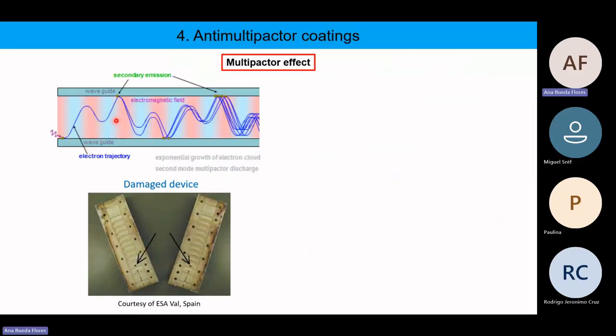So it is accelerated by the radio frequency field, and when it crashes into the walls of the waveguide, it creates secondary electrons. These secondary electrons start with low energy, but then they are accelerated by the field, and when they crash, they create new secondary electrons. So at the end, you can have a cascade of secondary electrons. The least dangerous scenario is just an electromagnetic noise that perhaps can prevent the communication with the satellite. But in the worst case scenario, if it exhibits high intensity, it can physically damage the device.